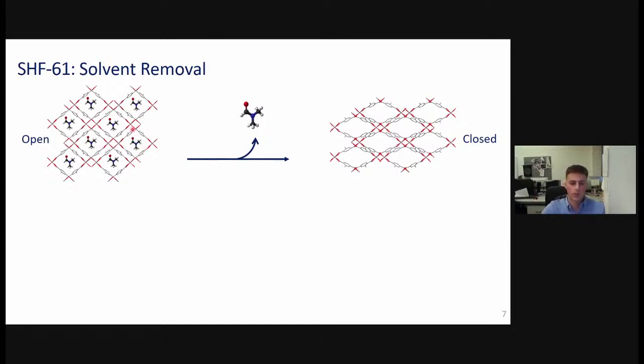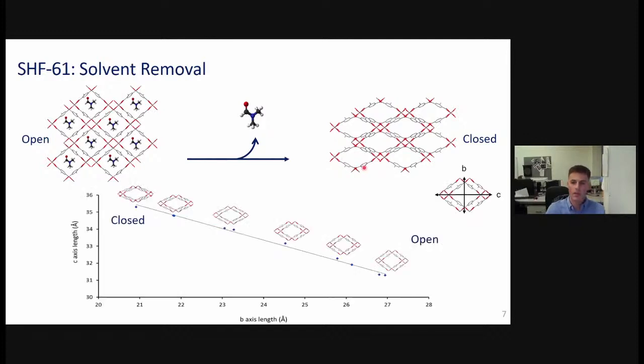So we can take single crystals of our initial framework containing DMF within the pores, and if we heat it up to a high enough temperature, what we see is that DMF can be driven out of the pores, and we're left with a transition to what we refer to as the closed pore form of the framework. So the pores narrow and reduce our accessible void volume. Rather than this being a defined transition between two discrete states like we saw for MOF-53, what we actually see is a continuous breathing mechanism where we can access a whole continuum of structures from our most open to our most closed pore form.